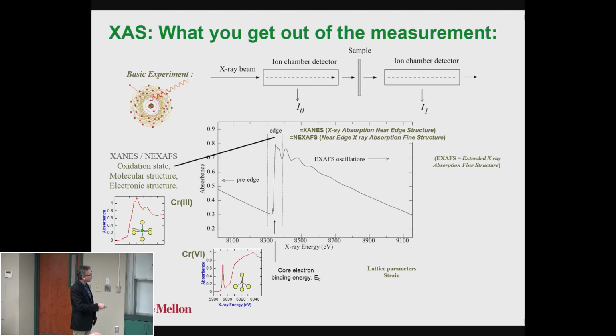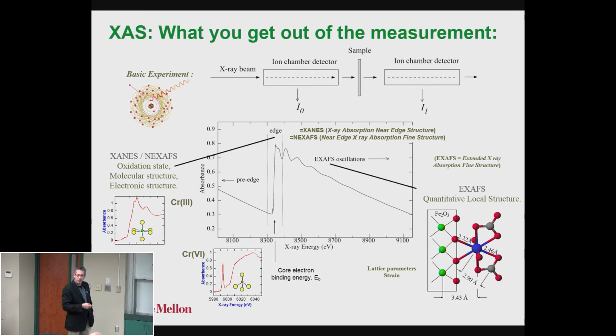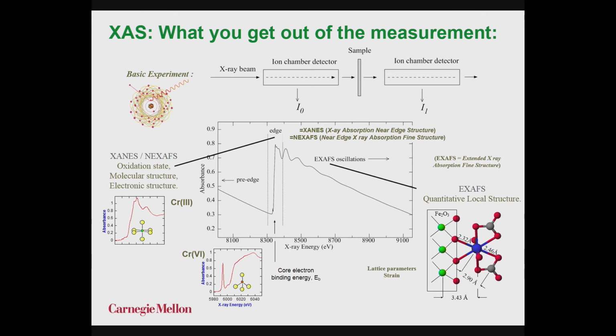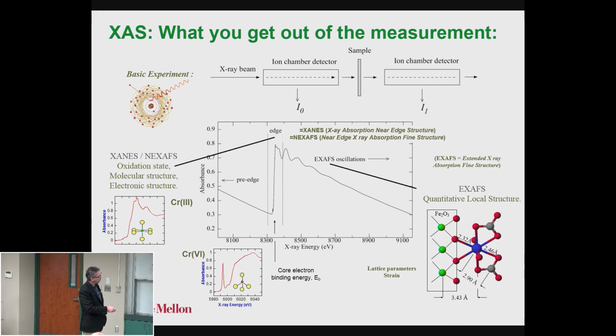If you keep going further out in energy, you end up in what we call the EXAFS region, which is extended X-ray absorption fine structure spectroscopy. That's this part. And this part gives you a little bit more information about the material farther away from the central atom. So for example, if I have a metal atom that I'm probing, with these squiggles right here, I can figure out exactly how many of these red atoms are around this central atom. I can figure out what distance they are. I can really understand how this metal is in the system.